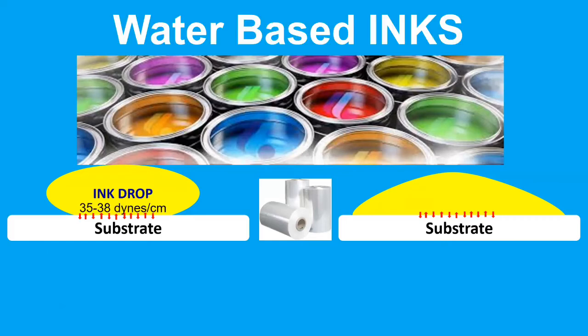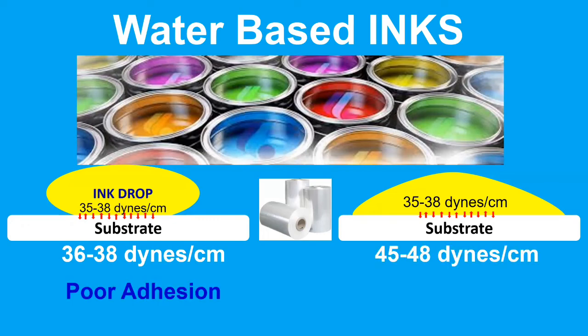If we are using water-based inks, and our surface tension of ink is 35 to 38 dynes per centimeter, and we are using a substrate with 36 to 38 dynes per centimeter, what will be the result? The result will not be satisfactory. The printing result will not be of good quality. Ultimately, we will have weak ink adhesion with water-based inks.